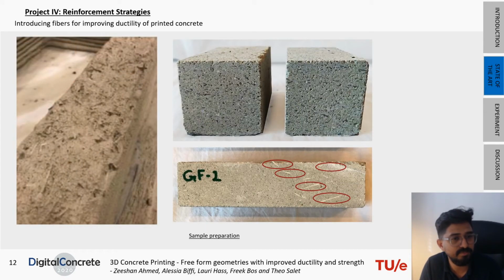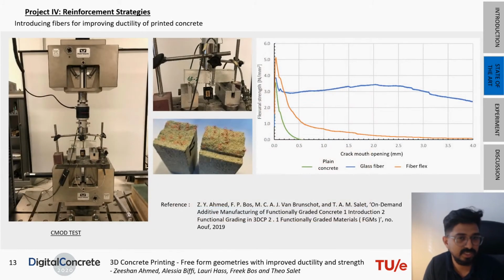Once the printing process is done, samples were prepared, and as you can see in the figure, you can clearly see the fibers in the samples. These samples were tested with a CMOD test, and comparing the test results of plain concrete and the samples with glass fibers, you can see significant improvement in the ductility of the samples. More details of these test results can be found in the reference given below.